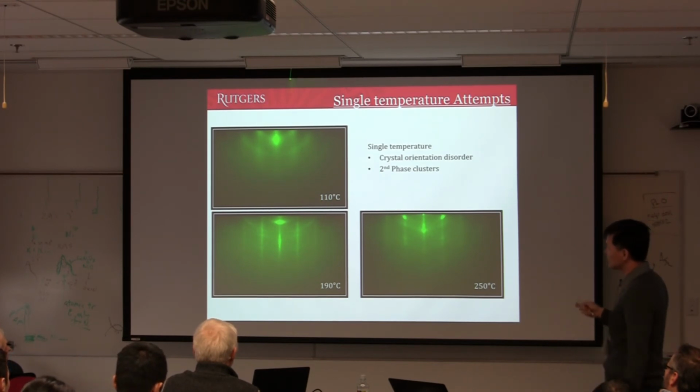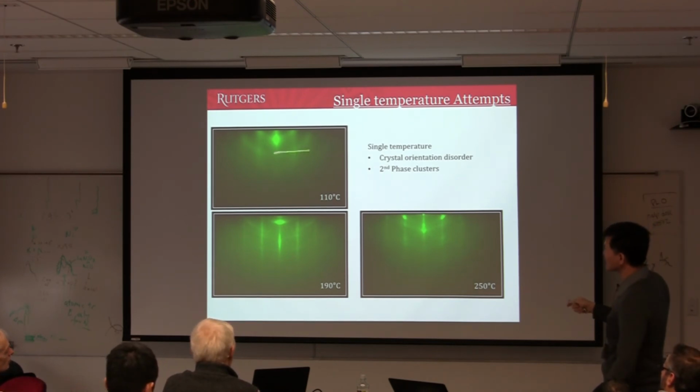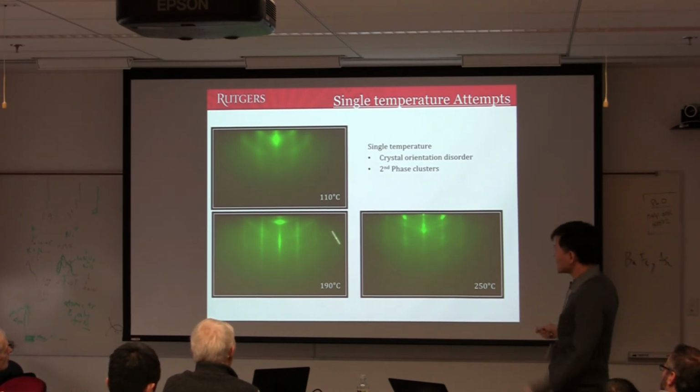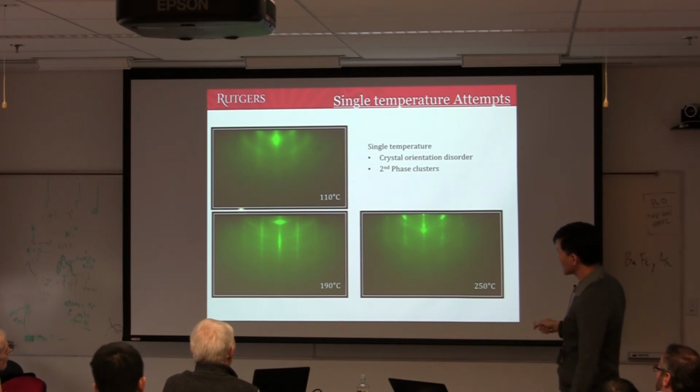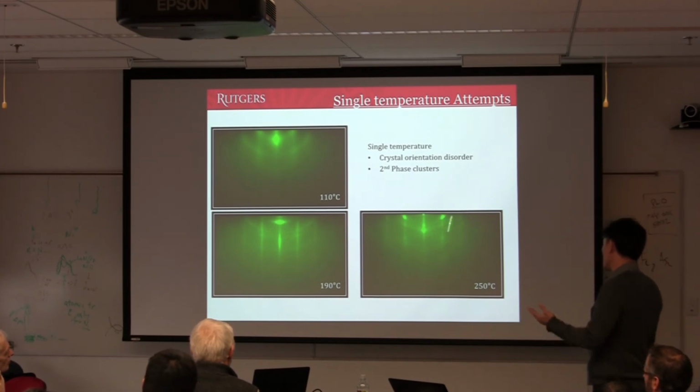Oh, it doesn't look good, because good means the very shiny streak pattern. Oh, okay, this is not good. Probably the temperature is too low. Let's raise the temperature. Oh, shoot, there are some rings. That's not good. Let's raise it further. Maybe that's because the temperature is too low. Let's raise it further. Oh, still not good.